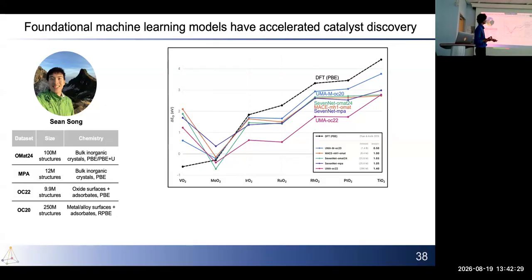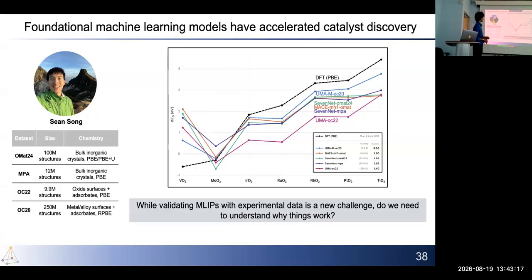To walk through this example, we have a bunch of rutile chemistries on the x-axis, and we were looking at oxygen vacancy formation energy. The black trend is the one that comes from DFT. Generally, all of these machine learning models capture the trend, so they go in the same direction. But you see that there's a pretty big offset depending on which model you choose. This is pretty encouraging in that it took probably a few hours or days to run, while the DFT probably took months or years to get to this point. So we're still figuring out how to actually use this. Can we use this to narrow down the type of chemistries we'd be interested in, and then maybe go back to DFT? That's still an ongoing investigation.